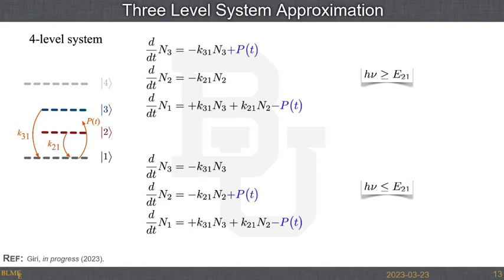So all of these equations here are dn/dt proportional to n. First order differential equations. What's the solution? I've got the first derivative equal to some constant times the function itself. Exponentials. So what I expect to see from this sort of picture is that all of my populations are going to be some sort of exponential decay. I'll come through with my pump, I'll put everything up in there, and then everything is going to drop down, and the phenomena that I want to pick up are all of these k's, these rate constants. So when I do the numerical modeling of all of my data based on this approach, this is the sort of numerical model that I'll want to fit to everything.